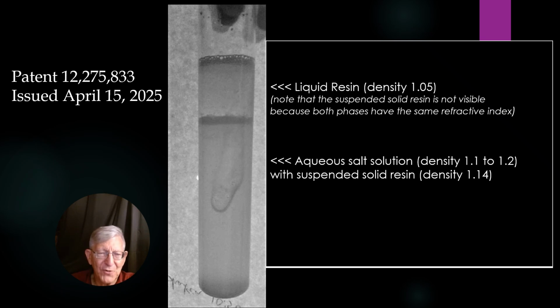And that's sort of demonstrated at the top here. You'll notice the top layer here is the liquid resin, which has a density of about 1.05. Either you look at specific gravity or you look at grams per mil. And there's actually a piece of solid sticking up into it. You can barely see that there's something there, but you really can't tell much about it because the refractive index of the solid and the refractive index of the liquid resin are basically identical.